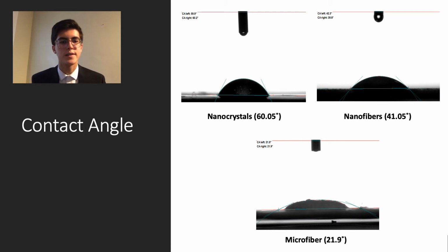Contact angle is a technique that looks at hydrophobicity and hydrophilicity by adding a water droplet onto a dried membrane of a given material. So this reveals that nanocrystals have an average contact angle of 60.05 degrees, followed by nanofibers, which have an average contact angle of 41.05 degrees, and microfibers, which have an average contact angle of 21.90 degrees. The smaller average contact angle in microfibers is due to a more porous surface compared to nanofibers and nanocrystals, where that water droplet can flow through more efficiently. And so in the nanofibers and the nanocrystals, you see less of that sort of open space where the water can flow through.